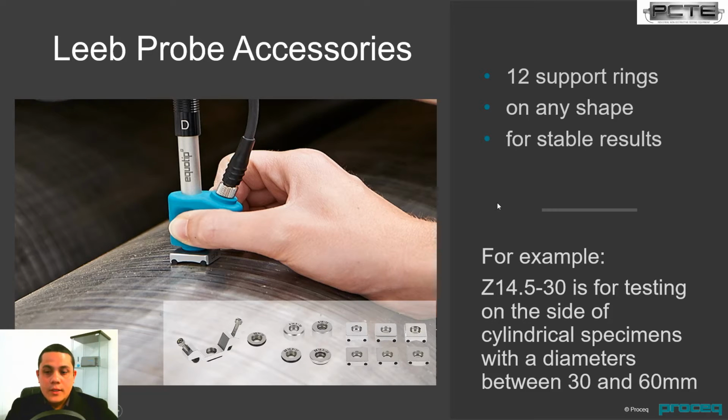So another consideration with Leeb is the direction of impact. As much as you can, you want to be as close to perpendicular to the test surface as you can manage. And there are a range of accessories to help with that. So there's support rings for things like spherical concave, spherical convex, so the outside of a ball, the inside of a ball. There's also cylindrical concave and cylindrical convex, so the outside of a pipe or the inside of a pipe. There's also a universal support ring, and that one just gets you into weird and wonderful shapes. So it can do the job of some of the other rings, but also get you into some weird and wonderful places so that you can actually get a decent result out of your Leeb. So for example, something like the Z14.5-30 is for testing the side of cylindrical specimens with diameters between 30 and 60mm.